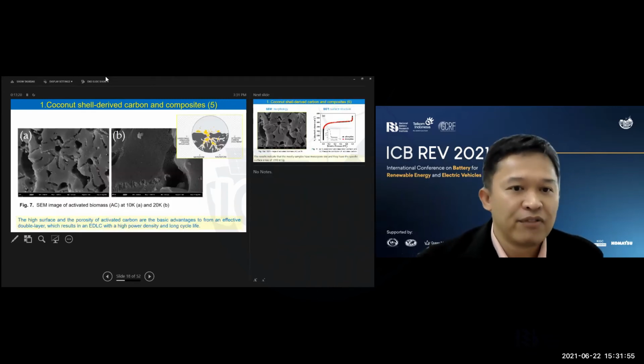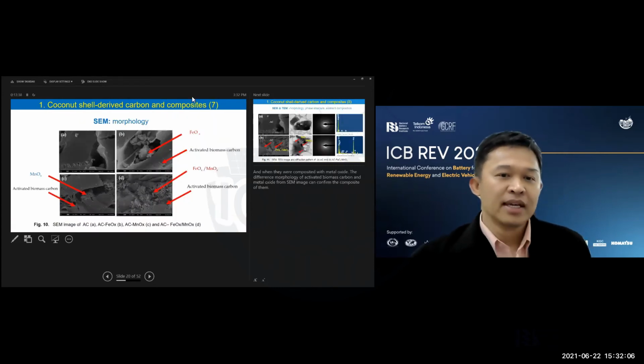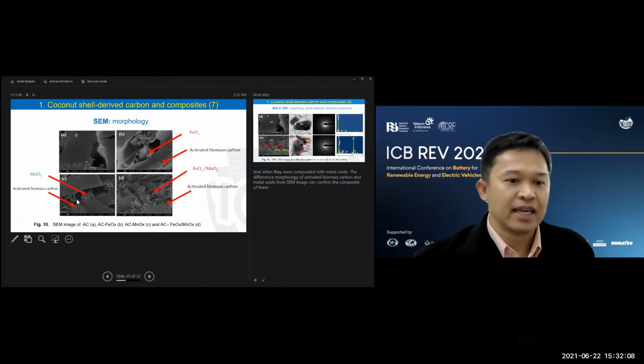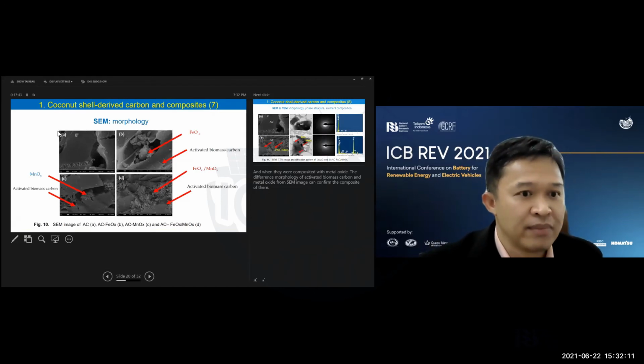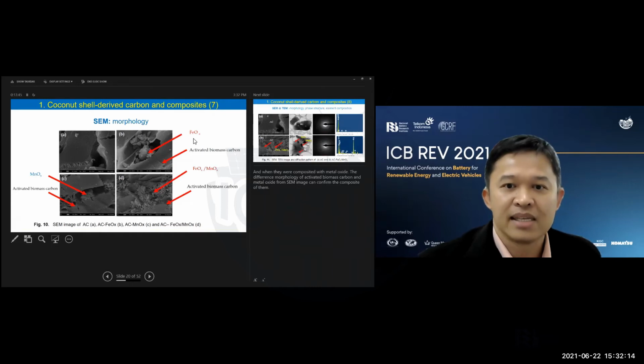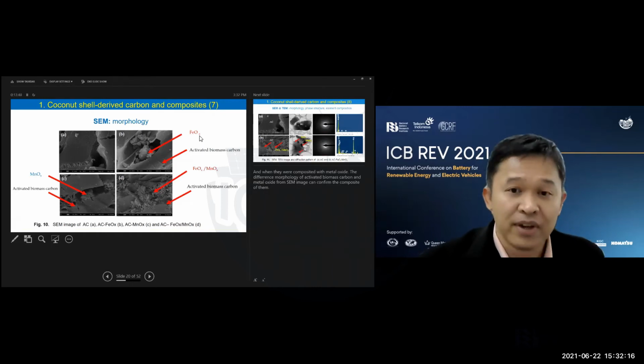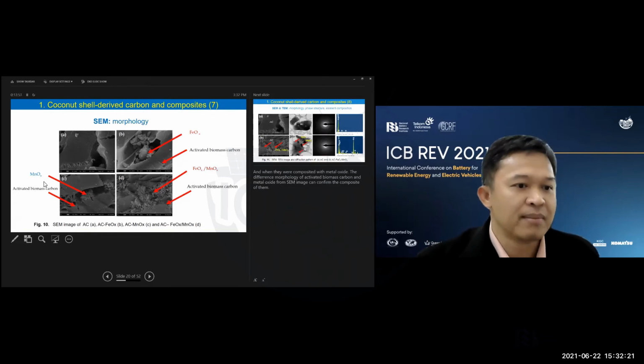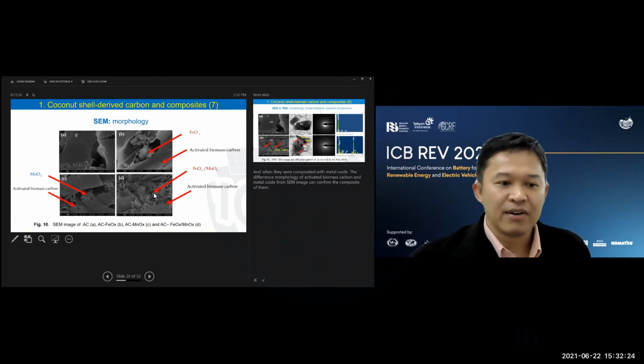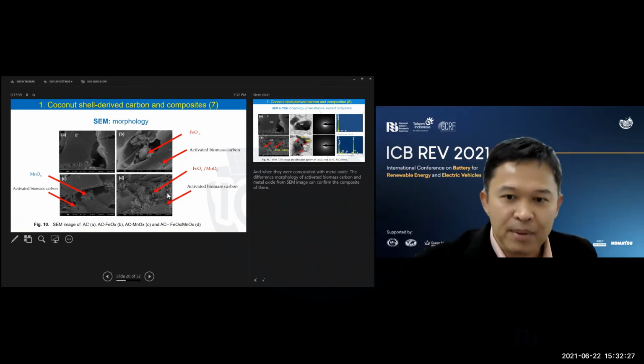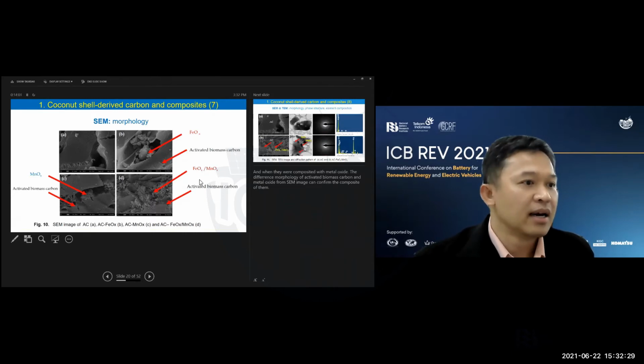This is the morphology study by scanning electron microscope. This is the pure activated carbon. And this one is the morphology of the activated carbon from figure A, and B is the carbon with iron oxide, and C is the carbon with manganese oxide. And for figure D, we prepare the activated carbon with iron and also manganese oxide combined.